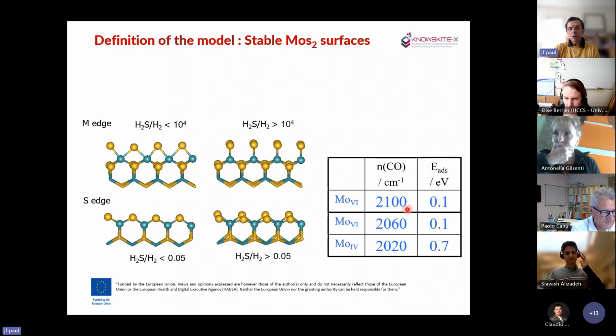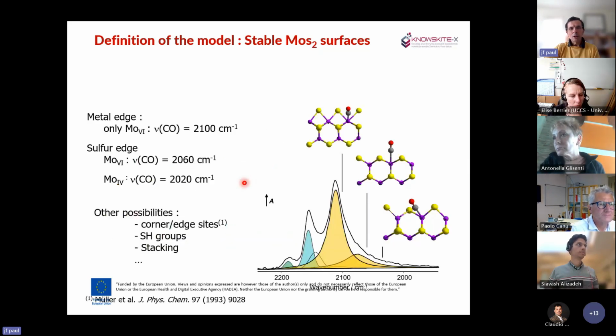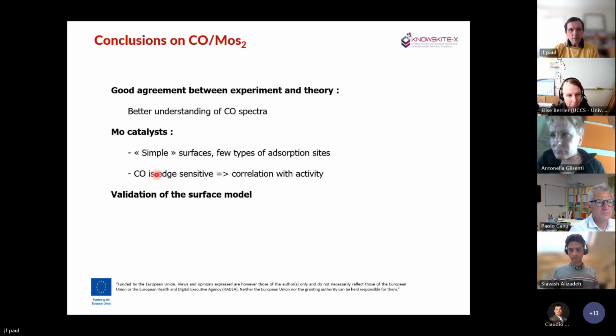So it's important to take that into account if you want to build a model. And we have computed the frequency and the adsorption, and you see that the differences are not so large from what is observed experimentally, and so it allows us to propose an assignment of the frequencies of the bands that have been observed experimentally. So it works quite well, but everything depends on the type of models that you define at the beginning.